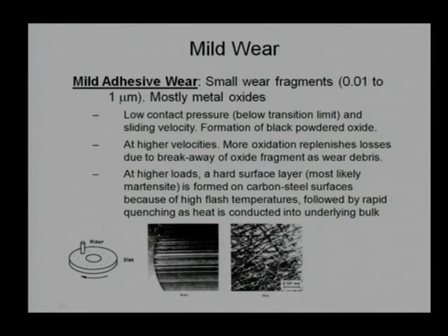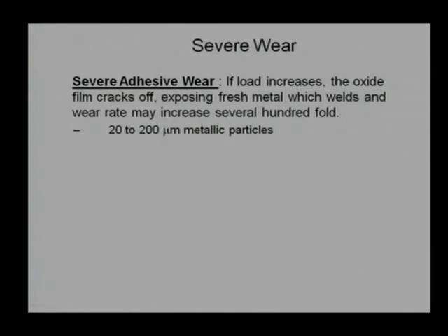And this is the surface of the disc. Even though we know the disc is rigid, stronger and has higher hardness, still at the micron level it gets scratches. So, when we do pin on disc machine experiments, we should replace the disc after maybe a couple of thousand hours if it is damaged. And this last picture, not very clear, shows smaller size particles. They are generally very small in size, maybe of the order of 1 micron or less. Now, shifting from mild wear to severe wear, what are the characteristics of severe wear?